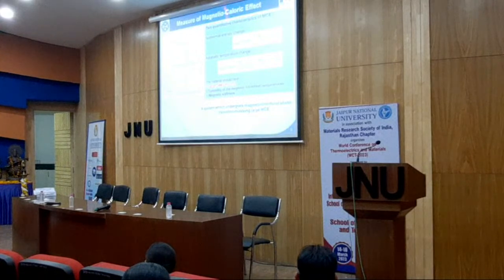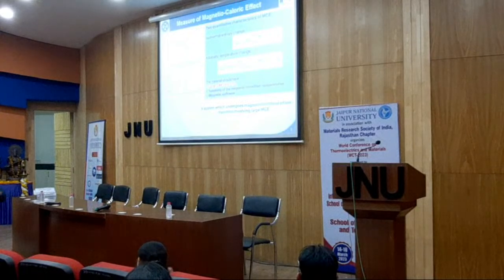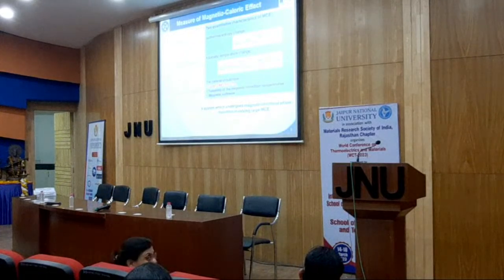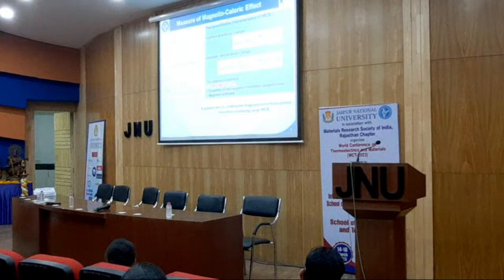To have this material for the required capacities, the material should have a large ratio. That means the sample should respond strongly to magnetization with a small magnetic field. The smaller the field, the smaller the capacity of the magnet you need. Then tunability depends upon the applications. Then the material should have softness, and it does not need large hysteresis, to avoid energy losses.